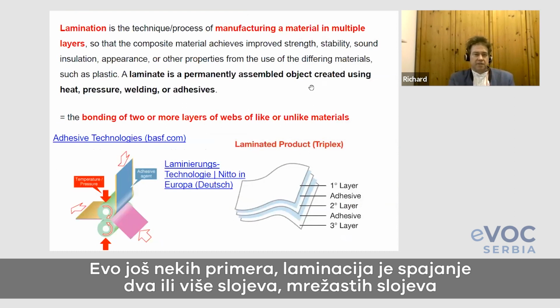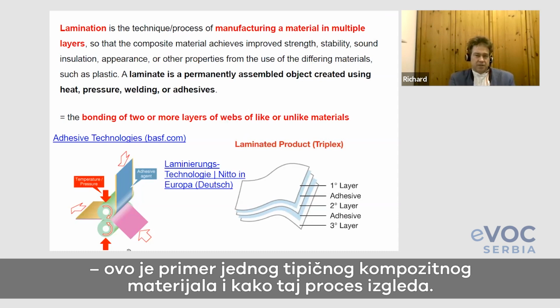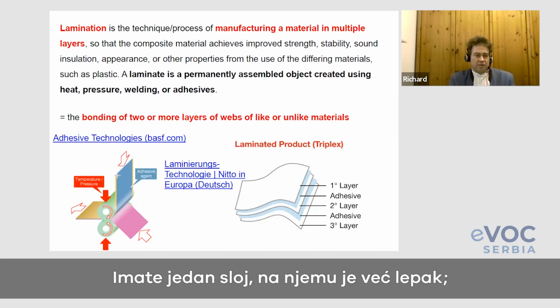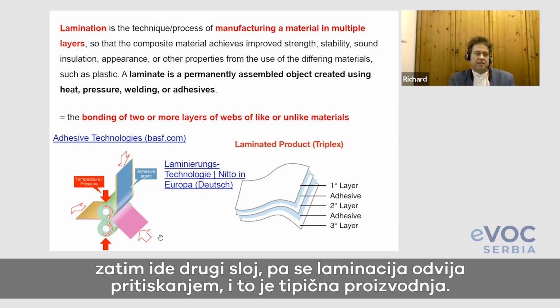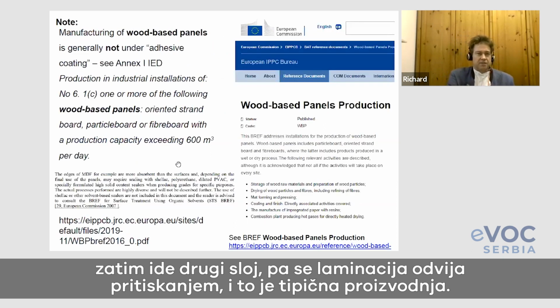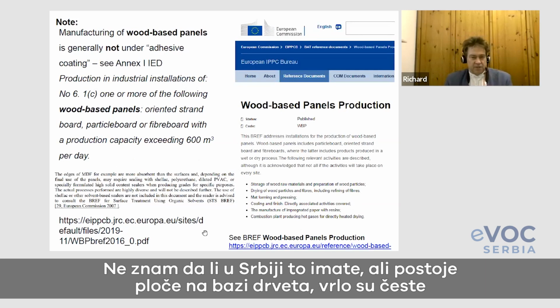Now, again, the lamination is the bonding of 2 or more layers of webs. That means on areas. So here is an example of a typical composite and how that process is working. You have, for example, here one layer where the adhesive is already on, and here's the second layer, and then the gluing or the lamination process takes place by pressing, and that is a typical production. One important thing is what I wanted to tell you.